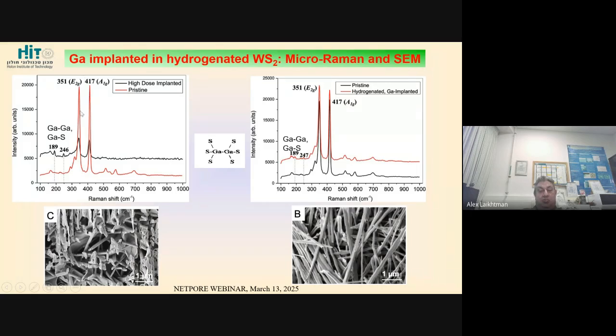When we implanted gallium by FIB, first of all, we observed the chemical change by micro Raman. Again, these two strong peaks are characteristic of WS2. As long as they are quite strong, it means that the structure is still as it was before, a good crystalline structure. For example, in this case, you can see a reduction of these peaks because of structure change at high dose. But we also have small peaks which are related to gallium. Again, we should remember that the gallium concentration is quite small, and the cross-section for Raman is also quite small, and this gallium was related to these kinds of structures from the literature. So this is a kind of proof of gallium implantation.